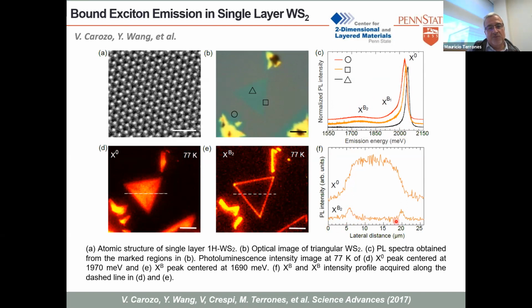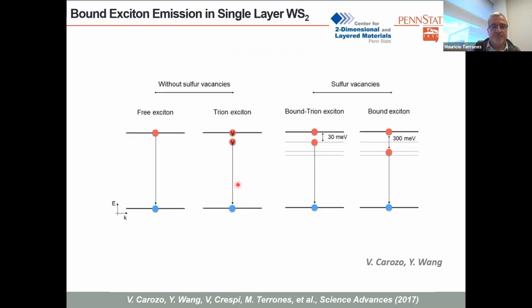So when you do the mapping of this one, you can see that this is on the outside. This neutral exciton is on the inside, and this bound exciton is on the outside. So you can see clearly here where the signal is coming from, right? So they are different. Yeah, this is the neutral exciton, this is the trion, right? And the trion is when two electrons and one hole come together, then you have 30 milli-electron volt difference, right? So in the band structure. But the bound exciton that we see is 300 milli-electron volts from this, right? So it's something different that is not the trion.